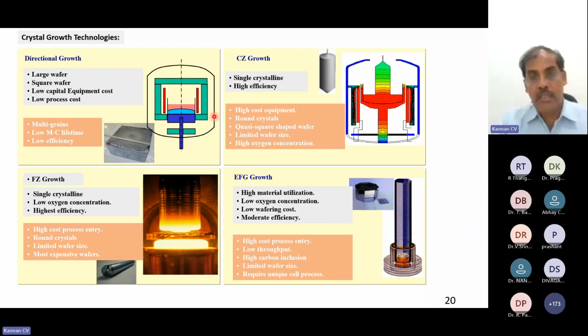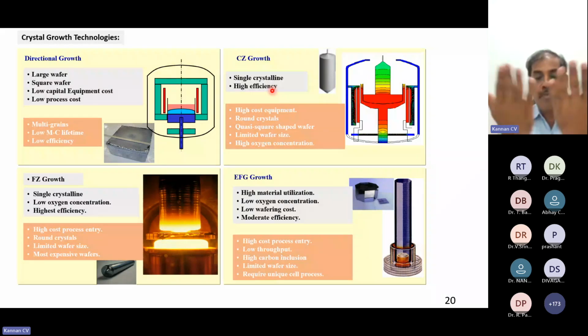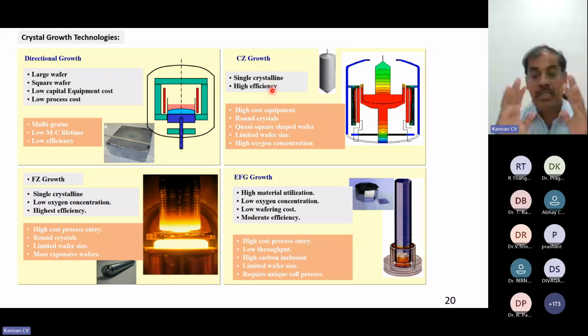And in contrast, if you see the CZ growth, it's single crystalline, instead of multi-crystalline, and since it's a single crystalline, the conversion efficiency is very high. But the problem is, you can grow only the cylindrical form, and you cannot increase the wafer size beyond a limit, because the crystal size is limited. You cannot increase the crystal diameter just like that. So wafer size is limited.